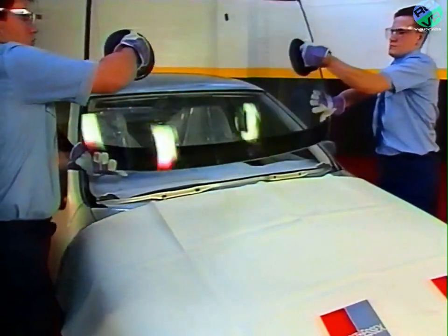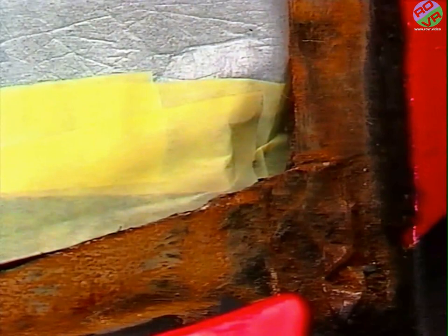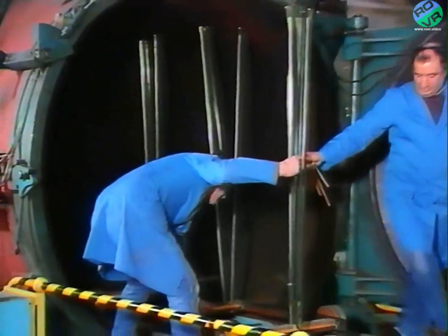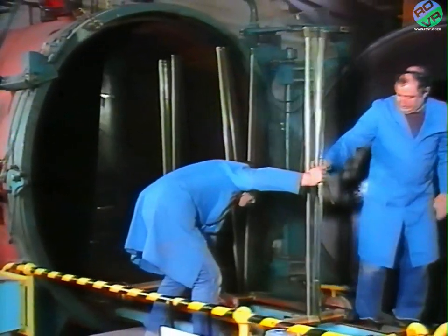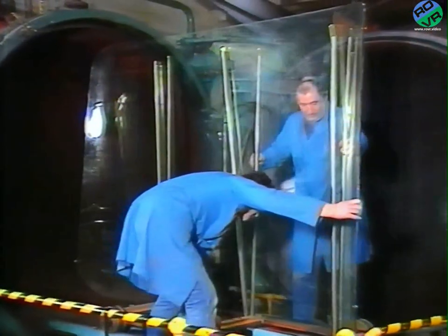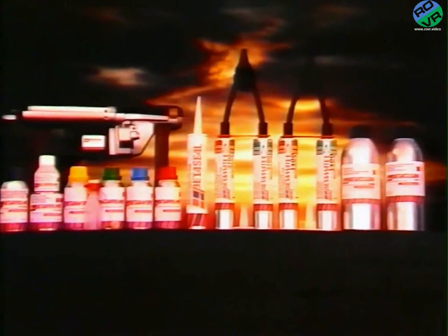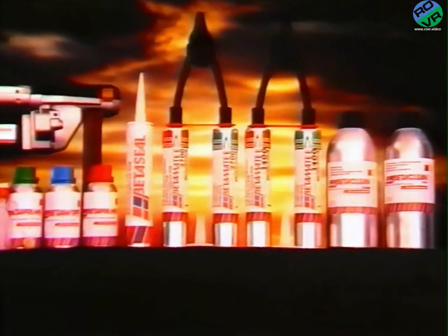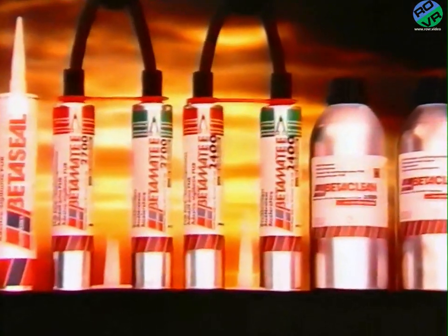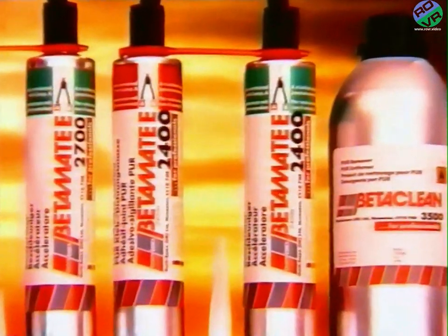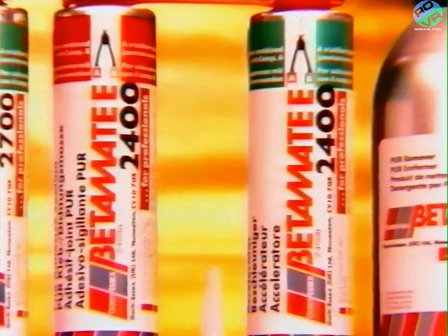For example, when the screen hasn't come out cleanly and there isn't a complete layer of old urethane, where there's bare metal around the aperture, where there's corrosion, or even when the job is so big and complicated that you need 30 minutes working time instead of only 10. The secret is in the fact that Betamate E is a system. There's a primer or an adhesive for every eventuality, a solution for every problem.